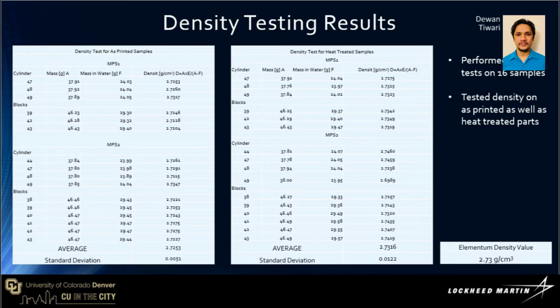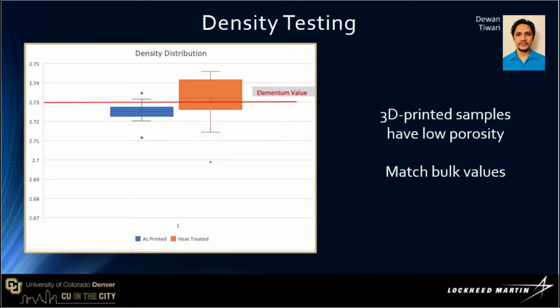In that case, we implemented a standard formula to analyze the density of 3D printed aluminum from different locations and orientations on the build plates. With the help of that, we were able to generate the density results of as-built and heat-treated samples. Collectively, the values of the as-built and heat-treated samples were averaged individually. Both results showed a low standard error, 0.051 for as-built and 0.0122 for heat-treated samples. This plot compares our result with aluminum, which is precisely accurate to 2.73 gram per cc on average for both the treatments.